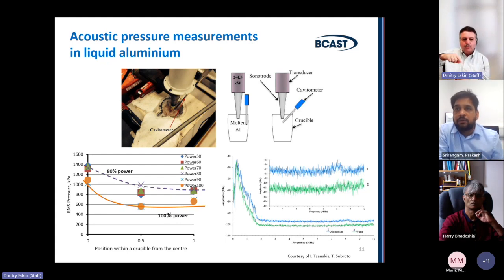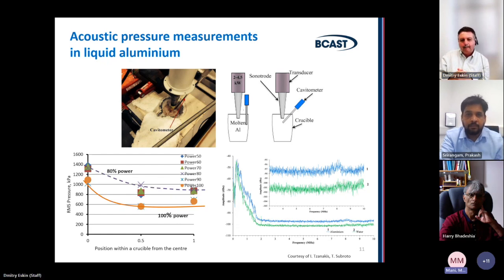And on the other hand, you don't want to go too high into temperature, because if you go too high into temperature, the absorption of hydrogen from atmosphere becomes more significant. So you degas, but you regas also at the same time. So you want to have a range where you can degas, avoid regassing, but have good kinetics of release of bubbles.